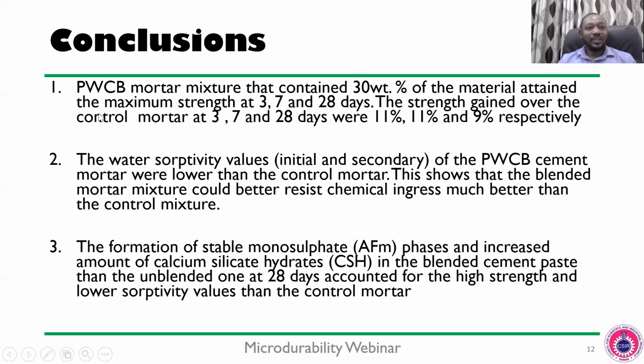So in conclusion, the clay brick powder mortar mixture that contains 30% of the material attained the maximum strength at 3, 7, and 28 days. The strength gain over the control mortar at 3, 7, and 28 days were 11%, 11%, and 9% respectively. The water sorptivity values of the PWCB cement mortar were lower than the control mortar. The formation of stable monosulfates, AFm phases, and an increased amount of calcium silicate hydrates in the blended cement paste than the unblended one at 28 days accounted for the high strength and lower sorptivity values than the control.